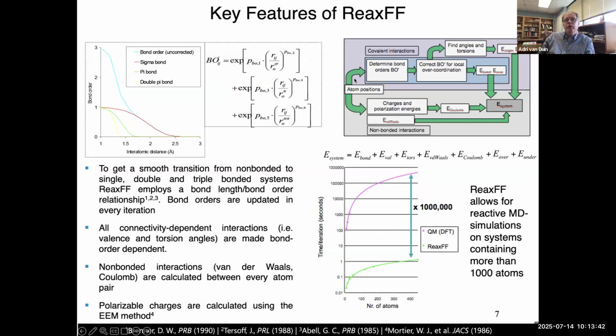So here's roughly how ReaxFF works internally. We start with the atom positions. We switch them between non-bonded and covalent interactions. So we calculate bond orders. We do a correction and then we find angles and torsions. And then eventually we calculate all the bond, angle and torsion contributions. Similarly, completely independently, we calculate charges. We calculate van der Waals interactions and Coulomb interactions.